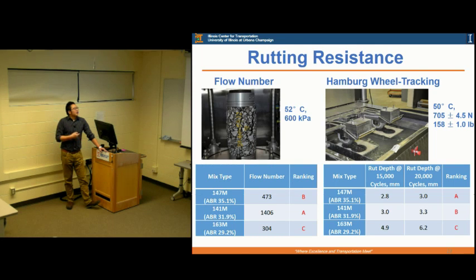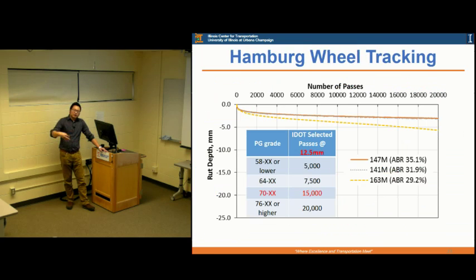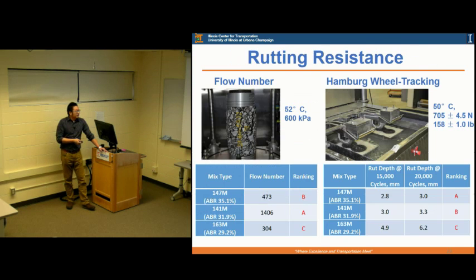This is a rutting resistance test. We have two methods: one is the flow number, and the other is the Hamburg wheel tracking. The difference is that flow number is air conditioned, so there's no water, and it's an unconfined test. For Hamburg, we are submerging it in water, so you run at the passes and get a different measurement. One is the rut depth, and one is the flow number.